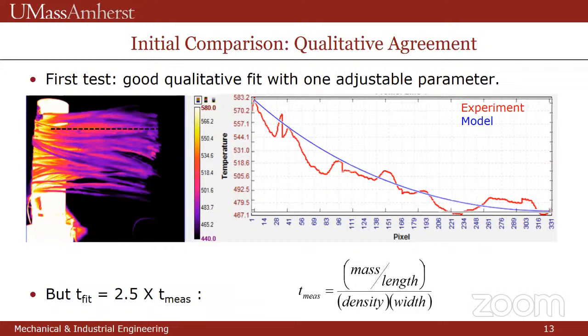And so you see bright yellow-white in this infrared image is the heat pipe. And then the kind of raggedy red and purple things are the carbon fibers hanging off. The braze joint is just along the left edge here. And it looks like victory. The blue line for the model goes right through the red line for the experiment, but only with one adjustable parameter, the effective thickness. And that turns out to be wrong. It's qualitatively correct, but the thickness doesn't match by more than a factor of 2.